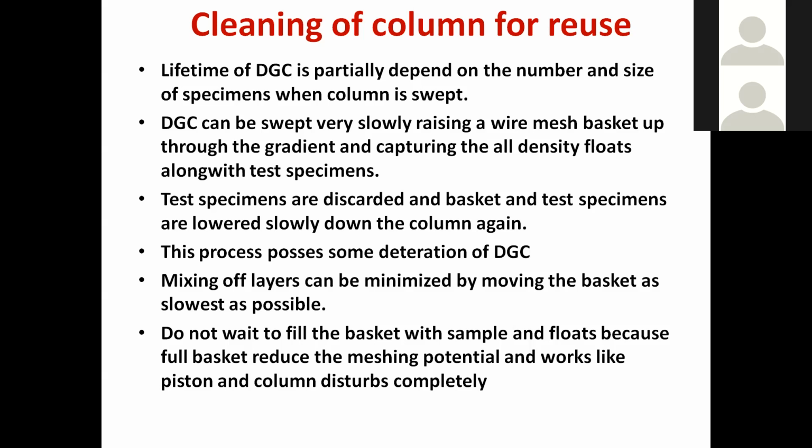Mixing of all layers can be minimized by moving the basket as slowly as possible. Don't wait to fill the basket with samples and floats, because a full basket reduces the meshing potential and works like a piston and the column is disturbed completely.